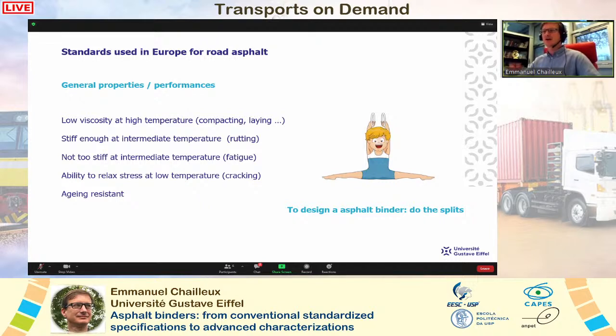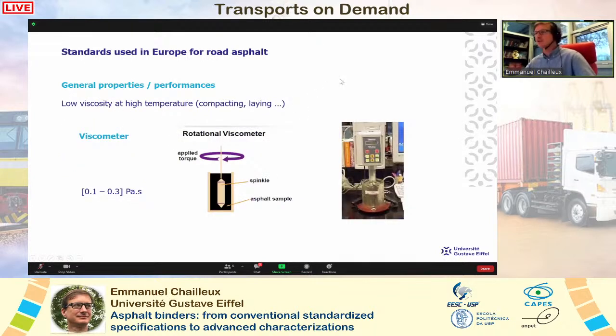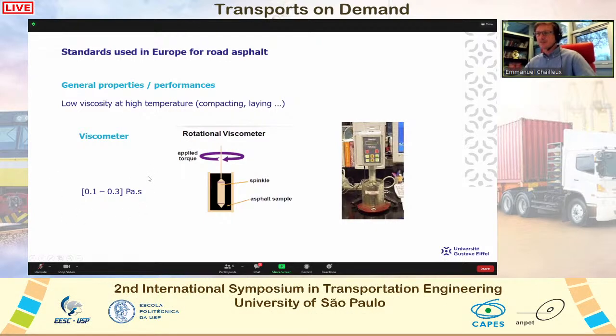Concerning the viscosity, it is generally measured using a rotational viscometer at high temperature, between 100 and 160 degrees. It's a very conventional measurement. And what we have to know is, in order to facilitate the process of mixing asphalt with aggregate, we need a viscosity between 0.1 and 0.3 Pascal second. It's very important if we want to coat the aggregate with the asphalt binder.